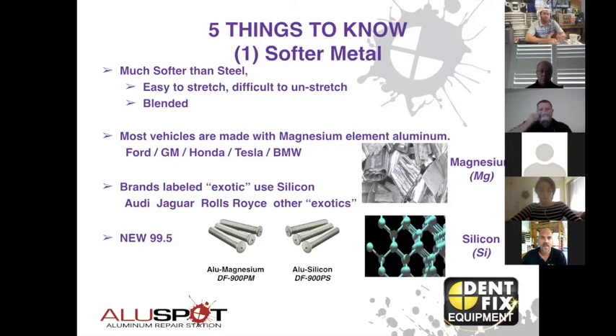Now, that's just a general rule of thumb. Always refer to your tech manual from the OE to determine what the power setting is, as well as what studs are proper for that panel. But as a nice rule of thumb, one way to know is to use the M or the S, or trial and error. If you use the wrong stud, it's going to pop, it's going to burn, you're going to go to pull it, and it's going to pull right off. You're not going to have that strong connection. So if you've got both bags sitting there, the alu magnesium and the alu-silicon, and you don't know, pop one or two of them on, give it a pull, and you'll know pretty quickly.